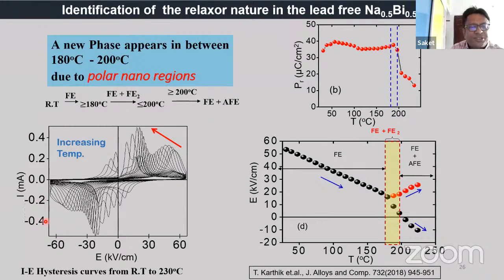Just see, this is the I versus E data of this material. This is with increasing temperature, from room temperature upward. Here you see that one switching field is there. Slowly this one switching field is converted into two switching fields, and with increasing temperature, one switching field is going to the other quadrant, the negative one. So it resembles that initially there was the ferroelectric phase with only one switching field, but at a particular temperature there are two switching fields. The second switching field slowly moves, and after a particular temperature it goes into the negative quadrant.